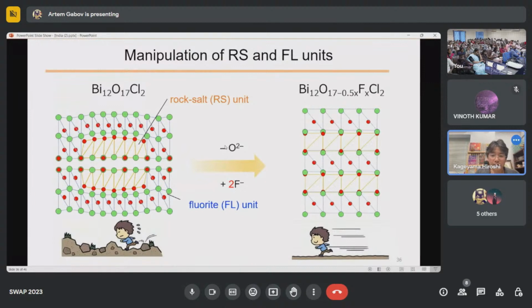So now, instead of the perfect fluorite structure, we found that actually this is an alternating stacking of the fluorite layer, rock-salt layer, fluorite layer, rock-salt layer, fluorite layer. So such alternation along this C-axis appears in the final compound. Namely, by doing topochemical fluorination, the crystal structure with the rock-salt and the fluorite units changes from this modulated structure to this alternating stacking layer structure.